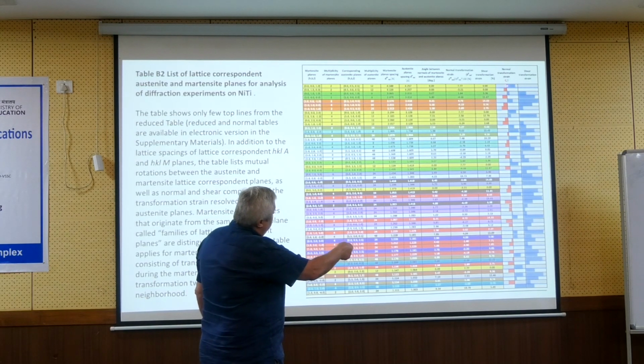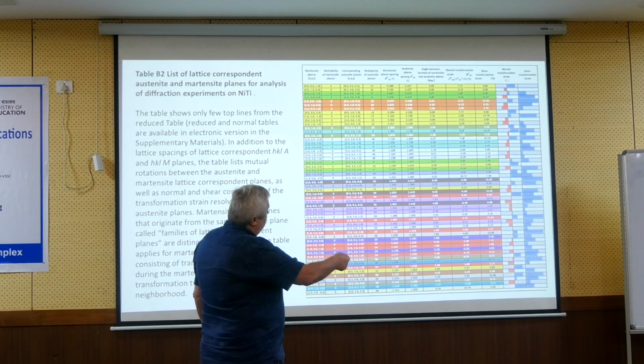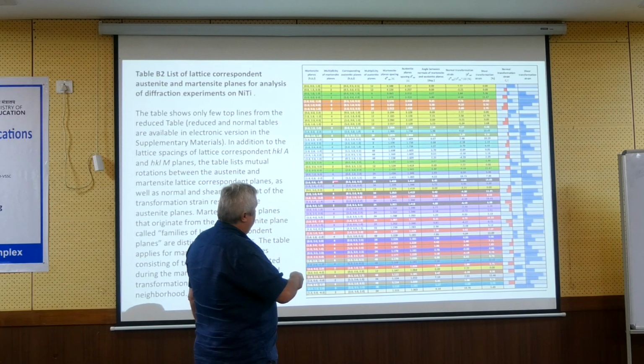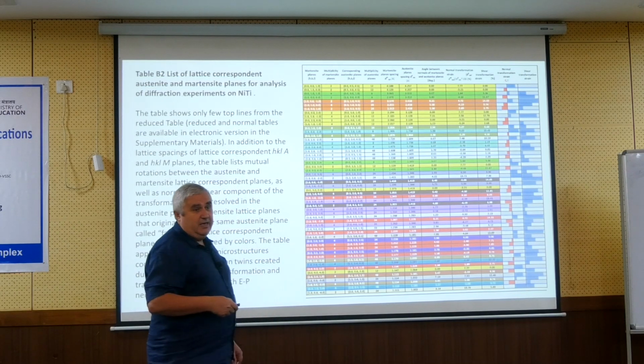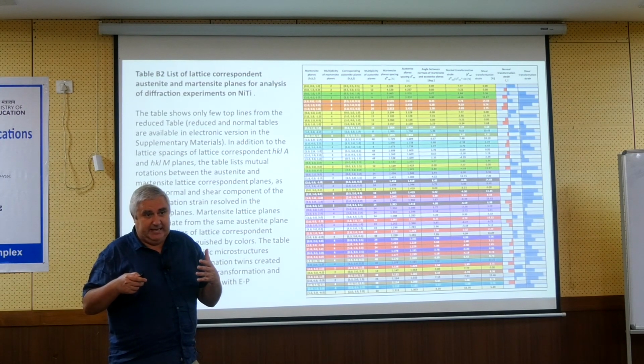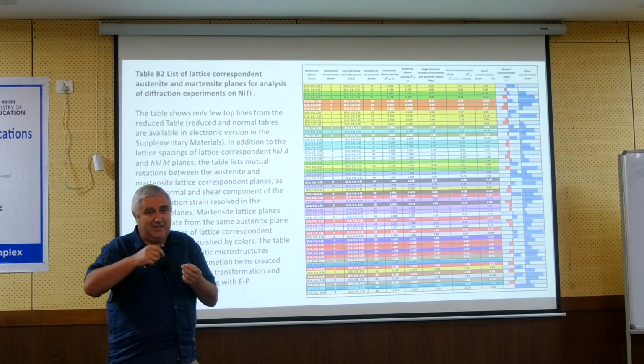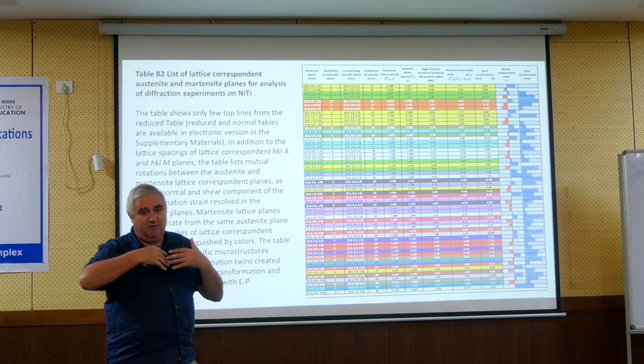This table, the compression is in red, this is in blue. So for example, if you look here, this one, which is 10 minus 3, will give you maximum deformation in tension. And really, if you look into the diffraction pattern, the 10 minus 3 reflection will be maximized because all variants are oriented into this direction.